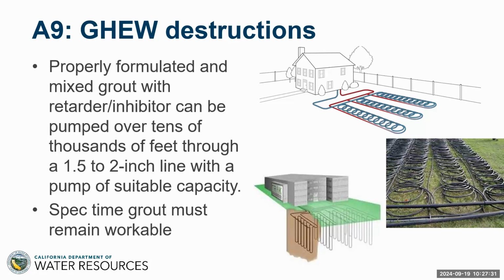Well, we know from our deep tunnel grouting that if you've got a grout line that's 1.5, 2-inch diameter or more, we can pump for tens of thousands of feet. We can either retard the grout, i.e., it'll just stay fluid for long, or we can do what we call inhibit the grout, which means that we basically put it to sleep and then we waken it up when we want it to be injected behind the tunnel lining, for example. So the key thing here is proper formulation, proper mixing, use of admixtures or additives, and specify the time the grout must remain workable. And that will be related to the contractor's equipment in terms of mixing and pumping capacity, and in terms of the length over which the grout must be injected.